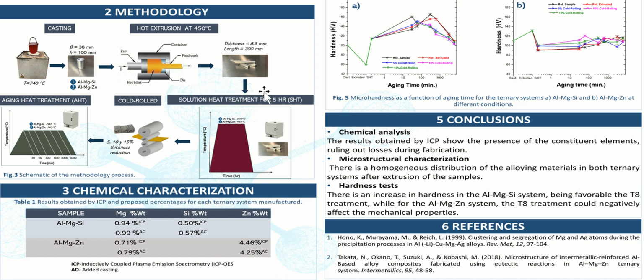Once the rods were obtained, the samples were cut into small sections to carry out the solubilized heat treatment, which was carried out in a Felisa muffle for 5 hours, at a temperature of 570 degrees Celsius for the system containing silicon and 465 degrees Celsius for the system containing zinc. Once these samples have finished the solubilization cycle, cold deformation is carried out on each ternary system, with a reduction of 5, 10, and 15% for each sample. To finalize the experimental stages, the samples are subjected to thermal aging treatment at different times, 30, 60, 300, 600, 3000 and 6000 minutes, with a temperature of 200 degrees Celsius for the samples containing silicon and 140 degrees Celsius for the samples containing zinc.